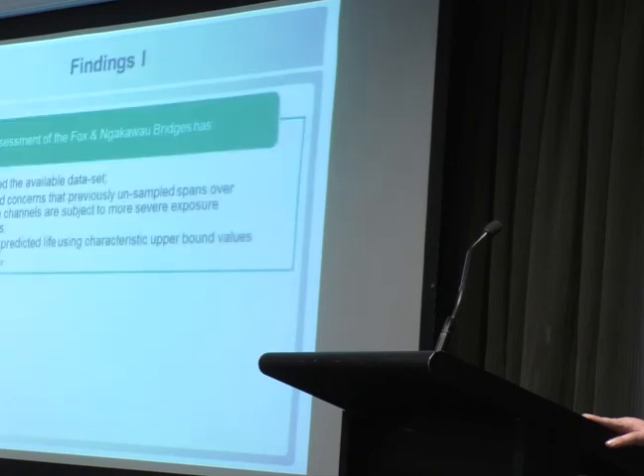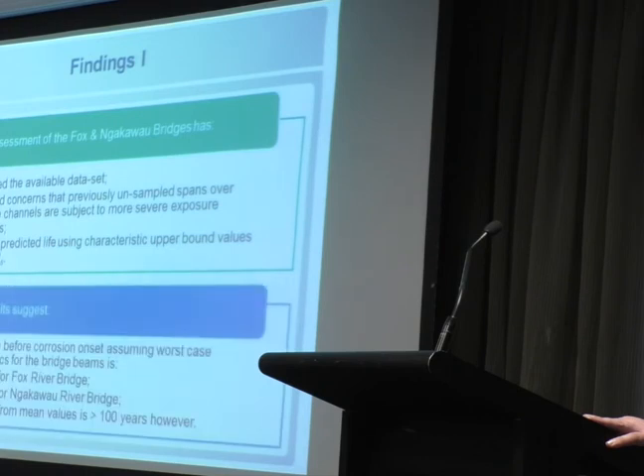So the findings with regard to the bridge, we expanded the available data set. We alleviated the concern that the previously unsampled spans over the estuarine channels were noticeably more subject to more severe conditions than the samples that were originally sampled by Rees, and we modelled the predicted life using upper bound values for the diffusion coefficient and surface chloride concentration.